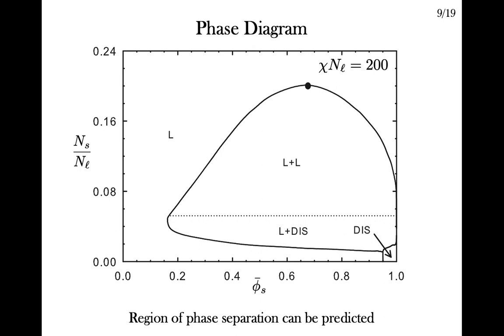This is an equilibrium phase diagram in terms of the ratio of polymer lengths on the vertical axis, and the fraction of the system that's composed of short polymers on the horizontal axis. At the top, we see that when the lengths are not too different, they mix together like in the scenario above, forming a single lamellar phase, like in the example I showed. As the short copolymers get down to about 20% of the length of the long ones, they start to phase segregate.